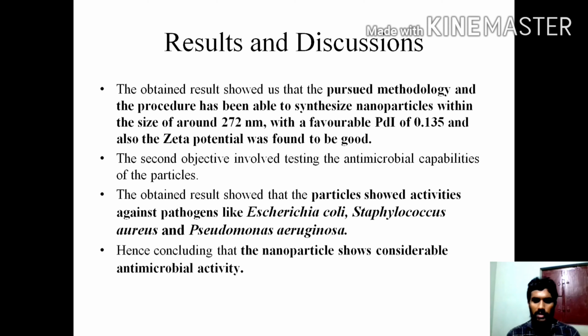The second objective involved testing the antimicrobial capabilities of the particles. For that, we had to do the microbe inhibition test, and the result showed us that the particles showed considerable activity against pathogens like Escherichia coli, Staphylococcus aureus, and Pseudomonas aeruginosa. E. coli and Pseudomonas aeruginosa happen to be gram-negative bacteria, and Staphylococcus aureus happens to be gram-positive bacteria. So we have been able to attain antimicrobial activity against gram-negative and gram-positive bacteria. Hence, we could conclude that the nanoparticles that we've synthesized show considerable antimicrobial activity.